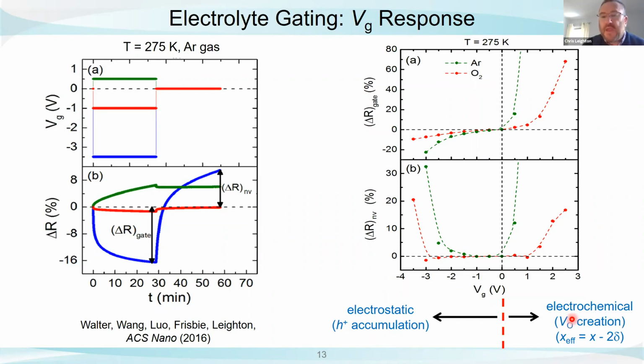I'll show you. On the other hand, at negative voltages, there's a significant window where the non-volatility is very small. And it's not until we go to the largest negative voltages that we get anything that looks like a non-volatile response. This is a suggestion that at least over a significant window, we could have something which is predominantly electrostatic, not influenced by the oxygen. And again, this is not proof, but it's something that I will return to later on. So we're going to show you a number of other probes that really emphasize this.